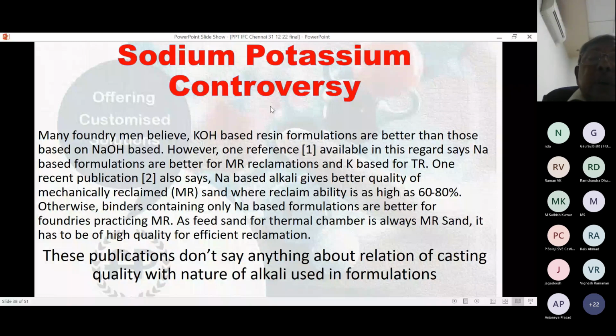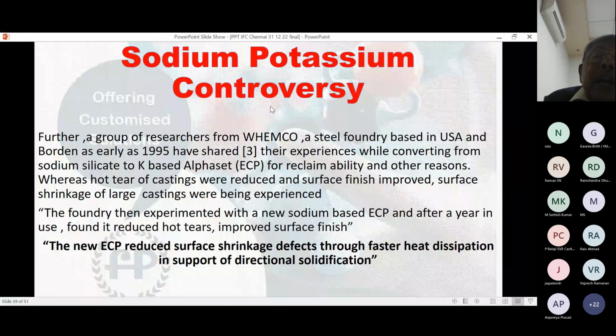Sodium hydroxide gives better reclaimability in the mechanical process, and potassium in the thermal process. They have not written anything regarding quality. But this is one more paper, where a group of researchers were converting a steel foundry from sodium silicate to the conventional first Alphaset, which was only potassium based. With the conventional potassium based system, when they converted, they found improvement: hot tear and surface finish of the castings were improved. While converting from sodium silicate to the potassium based system, surface finish and hot tear of the castings improved, but shrinkage in large castings was being experienced. That is using potassium based Alphaset.